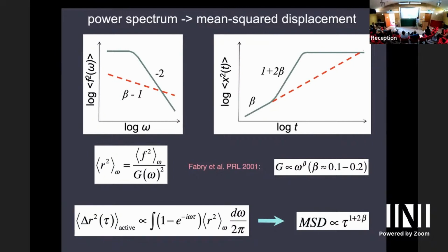There's actually a lot of confusion in the field, especially when people come more from the biology side. They say diffusive, superdiffusive, subdiffusive when they characterize mean square displacements. That's confusing because diffusive implies thermal excitation and not just the slope. So that's the first level of confusion. But in cells, when you see a power law where the mean square displacement scales with time like power 1, people say, oh, that's regular diffusion. But it turns out when you turn the power off, so if you take the myosins out, it falls way down. So it's not regular diffusion, it's active.